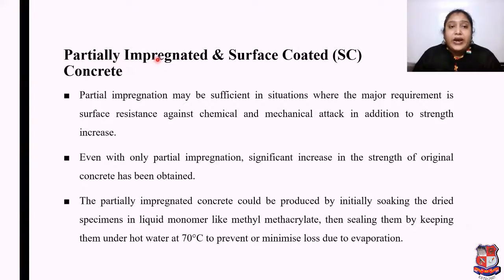Now, if we talk about partially impregnated and surface coated concrete, then partial impregnation may be sufficient in situations where the major requirement is surface resistance against chemical and mechanical attack in addition to strength increase. Even with only partial impregnation, significant increase in the strength of original concrete has been obtained. The partially impregnated concrete could be produced by initially soaking the dried specimen in liquid monomer like methyl methacrylate, then sealing them by keeping them under hot water at 70 degrees centigrade to prevent or minimize loss due to evaporation.